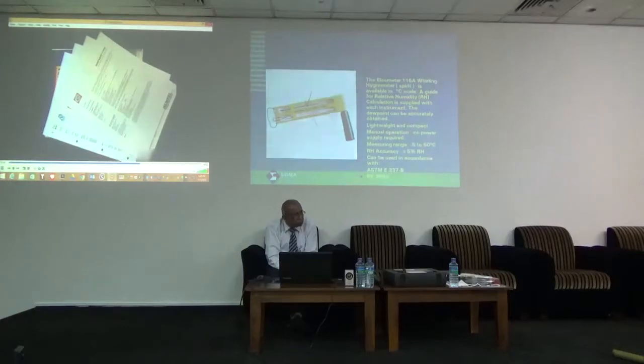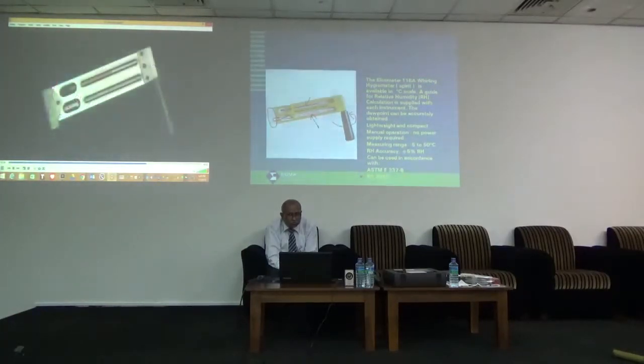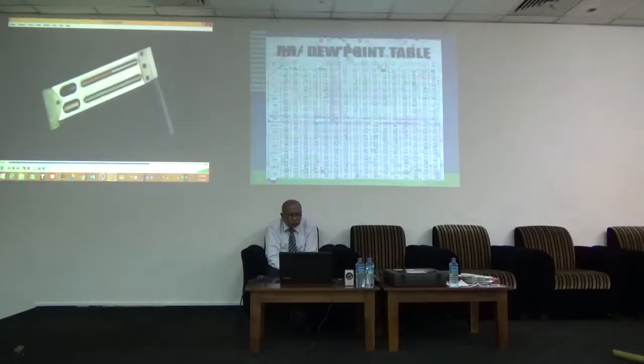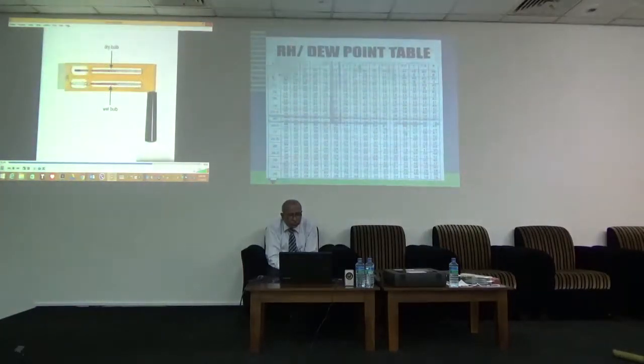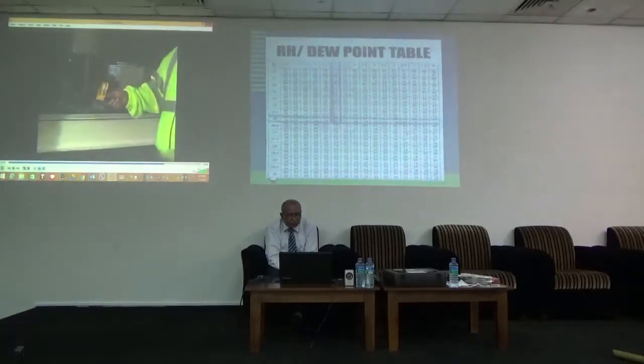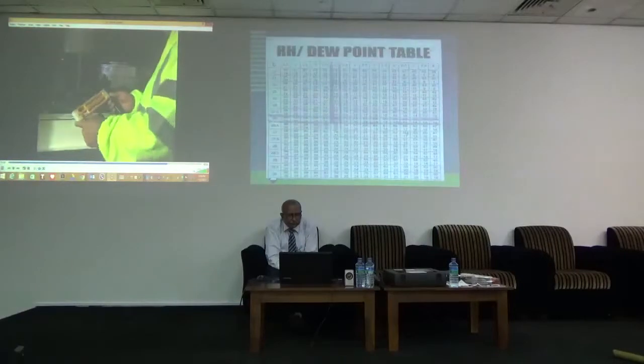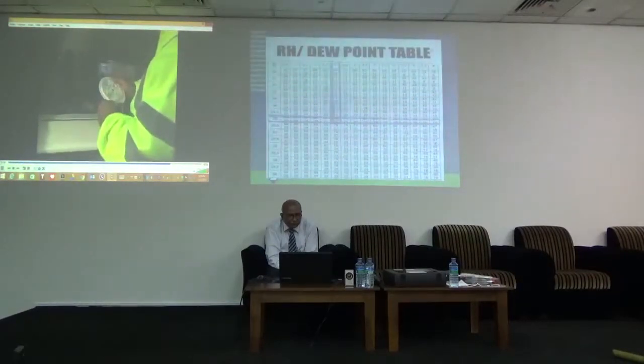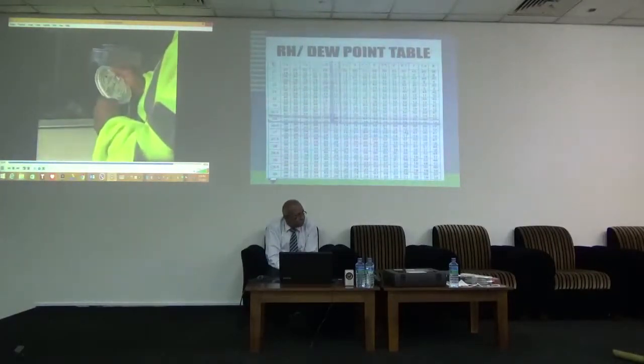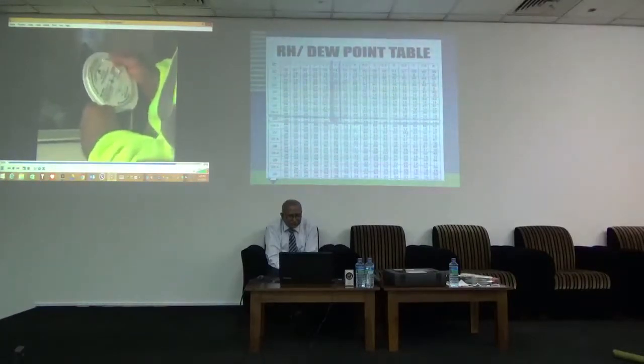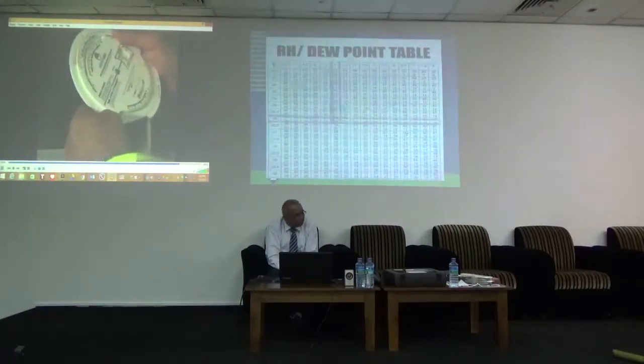To recap, establish the relative humidity criteria laid down in the specification or product data sheets. Check the whirling hygrometer for wear, tear and damage, and check that the bulbs are not broken. Also check the instrument has distilled water and that the wick is attached and clean. Whirl the hygrometer away from your body. Record the readings on both the wet and the dry bulbs. Finally, using tables or a calculator, assess the relative humidity against the criteria set in the paint specification or product data sheets.